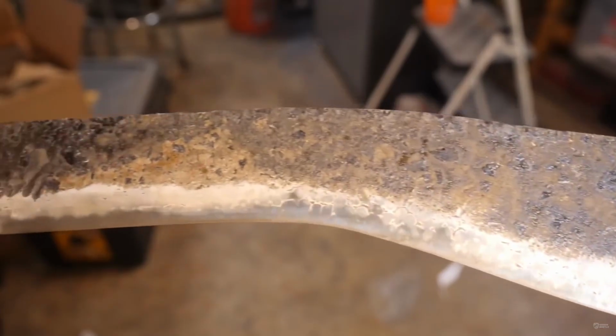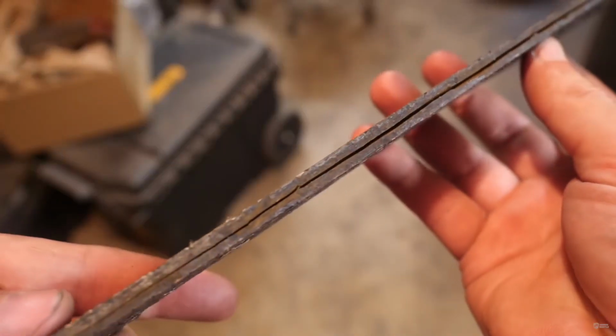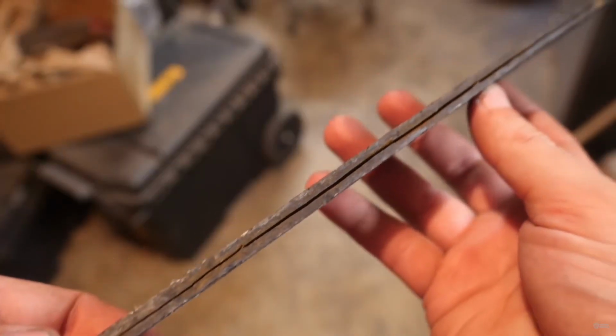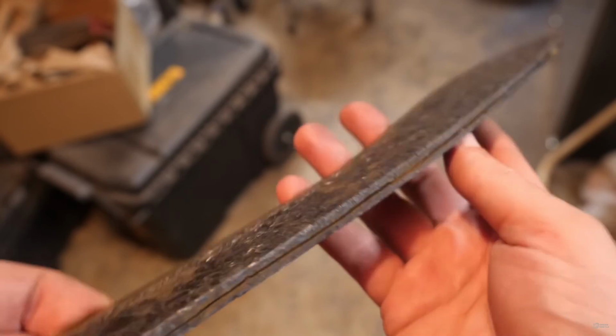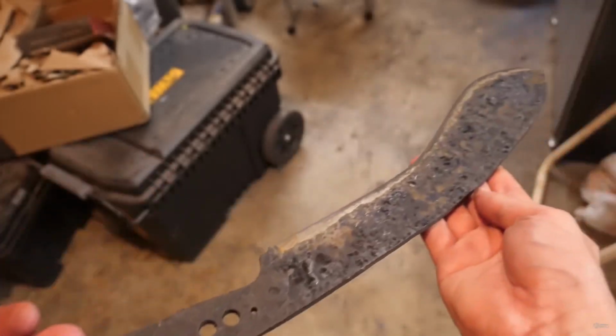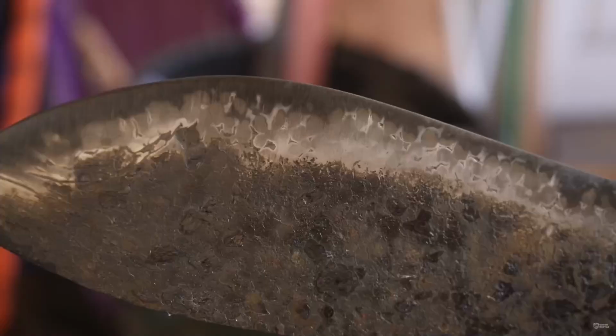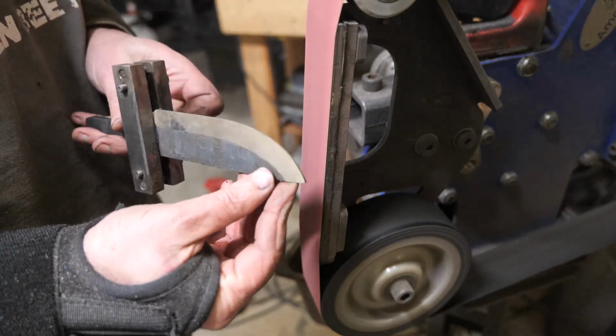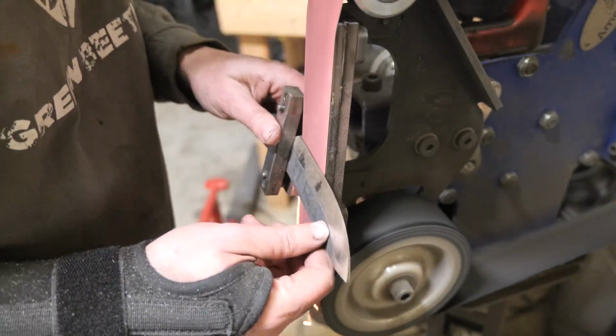This was a birdshot jacket on a core of, I think it was 1084. But when metal enters the austenitic state at high heat, it actually shrinks. And then when it goes to martensite during the quench, it expands very rapidly. And dramatic things happen. You can think of a katana, which goes into the quench straight, but because the spine is clayed and only the edge undergoes martensitic transformation, the force of that expanding martensite along the edge is strong enough to actually bend the katana backwards towards the spine during the quench.